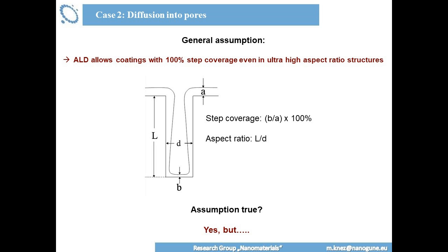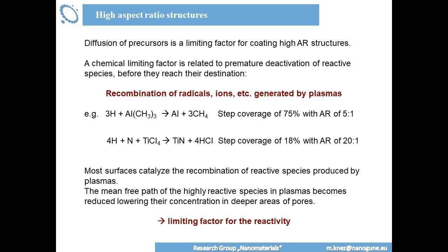Now, how can you get ALD having a step coverage of 100%? Well, you need to think about several issues. One of them is, for example, the chemistry. That's the utmost important issue to think about before you set up a process. What is your chemistry doing, and can your chemistry have an impact on your step coverage? And this is very much dependent on the stability of the precursors. You heard a lot about stability from Mikko Ritala yesterday.